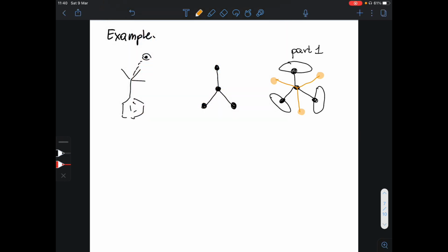And if you put atoms marked in orange in part 2, they will also form bonds to part 0, so to the carbon atom in the middle of the tert-butyl group, but the two parts will not create bonds, they will not be connected with each other. The atoms from part 1 will not be connected to part 2. So we'll nicely be able to look at the structure.